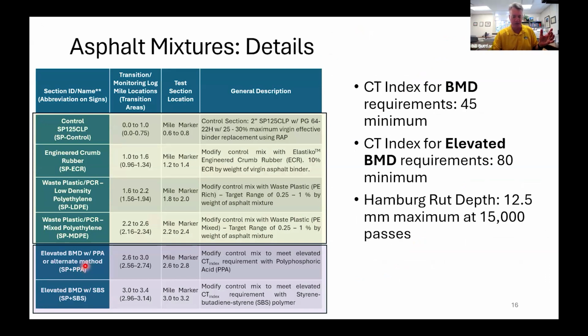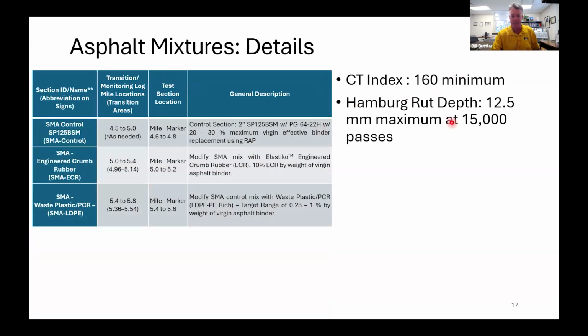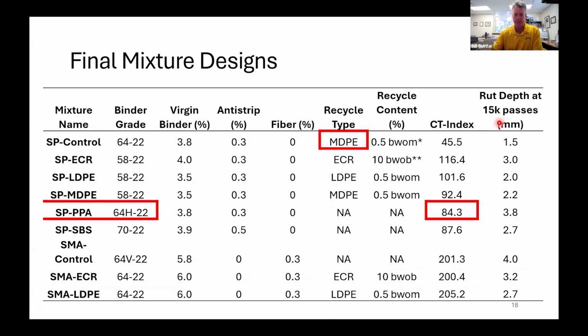MoDOT, a few years ago, was looking at minimum cracking test or CT index scoring, and they wanted to elevate it. So they had the contractor or us work on a couple of higher CT scores, like 80 and above, as opposed to the lower requirement for dense graded. Now, for SMA, they already had 125 minimum CT index. And as that rolls out, those numbers are clicking up. So we had dense graded standard CT requirement, dense graded elevated CT requirement, and then over here, the SMAs with a 160 score minimum. And this was a 15,000 pass location, but we did our designs with a 20,000 pass Hamburg.